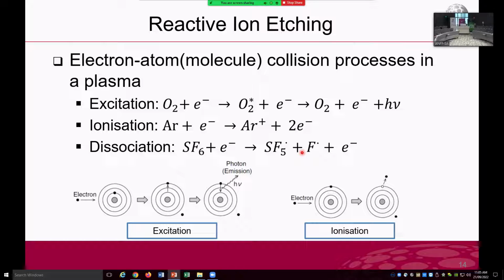And then, after reaction, the difference is that in the dry etching process, reactive ion etching, these dissociated molecules or radicals should generate etch products which are volatile, having high vaporization pressure. Otherwise, it's going to be difficult to remove this etch product, and then that etch product will slow down the etching process. But in the PECVD process, for example, this product should not be volatile. It should be involatile because you are actually collecting the product in your PECVD process. Right? So plasma is used in sputtering, in reactive ion etching, and in CVD processes, but the aim is a bit different depending on your use of plasma.